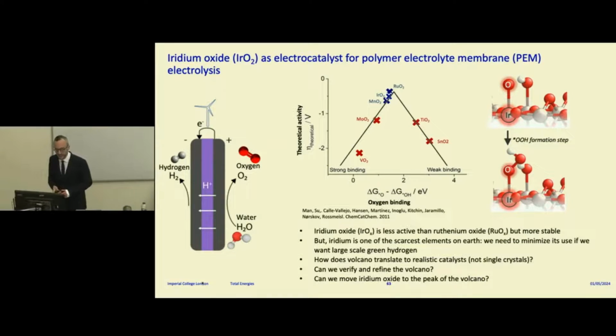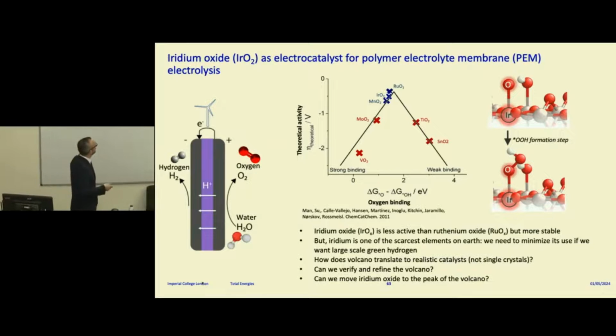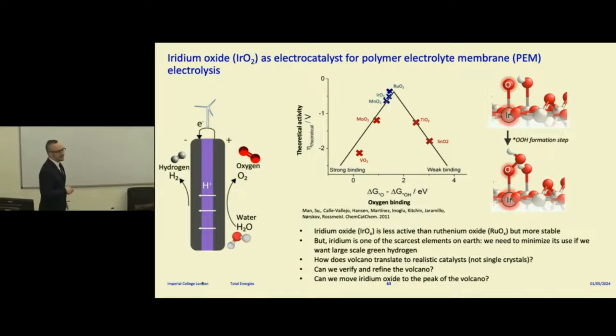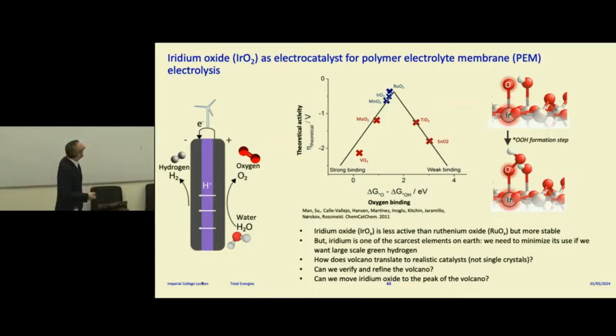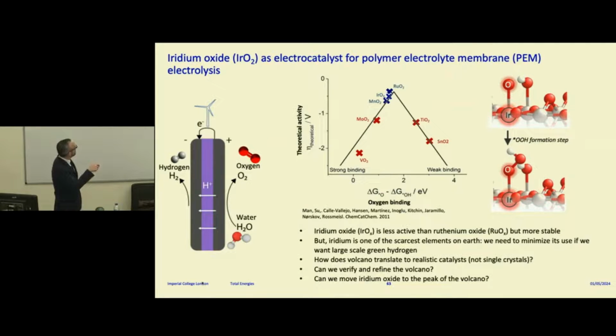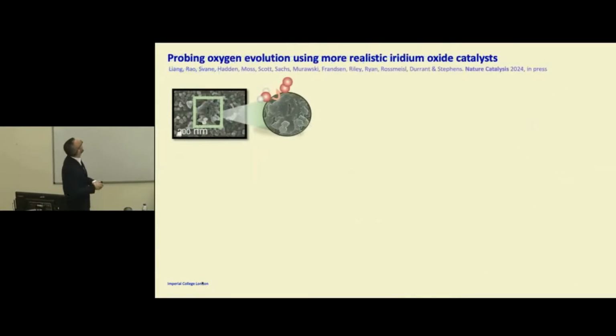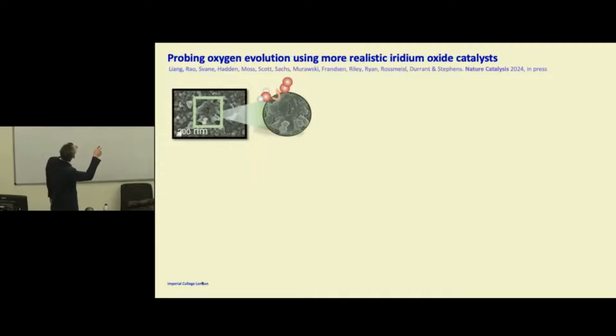There's a lot of talk now about making hydrogen at scale, but we're not going to do it if we use current technology. Often when we look for new materials, we discover them by serendipity, and that's the standard way to do it, but we'd like to be more intelligent and do it by design. It would be more fancy. So we have this volcano, which in principle is a design principle. I've shown previously that the volcano translates well for single crystals, but how does it translate to realistic catalysts? Can we verify it? Can we refine this volcano? And can we move iridium oxide to the peak of the volcano so we can minimize the amount of iridium that we use? So this is a typical example of the iridium oxide catalyst that we use.